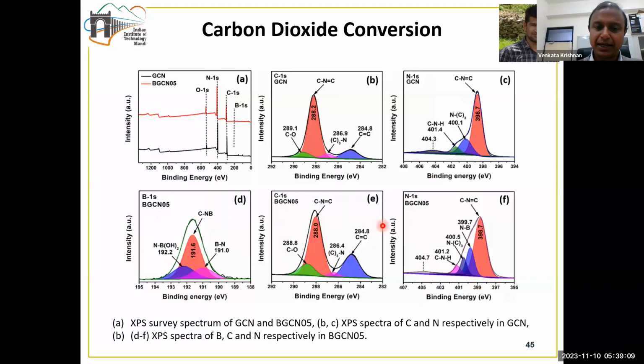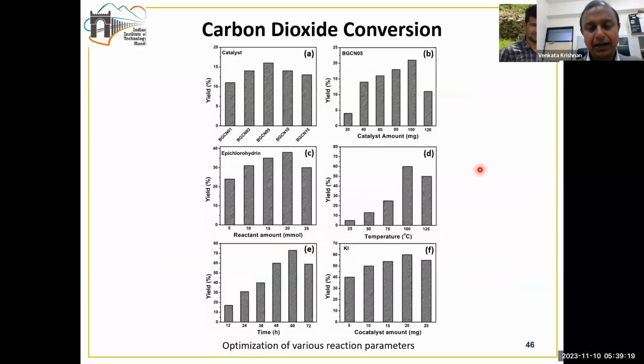Then we did the XPS analysis to understand the oxidation state of the various elements present on the catalyst and also the internal electronic interactions between the different elements in the catalyst. Then we did a detailed optimization of this reaction, wherein we optimized the catalyst first, especially the boron amount of the catalyst, and we found that the catalyst which is having 5-8% of boron showed the optimal, the best photocatalytic, best catalytic activity. Then we did the optimization of the catalyst amount, which shows the 100 milligram is the optimal amount. We optimized the reactant amount, we optimized the temperature, we optimized the timing of the reaction.